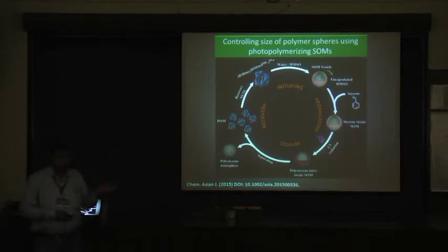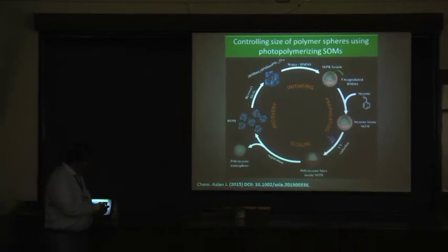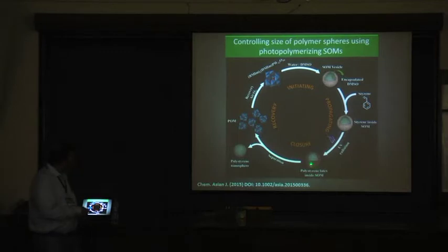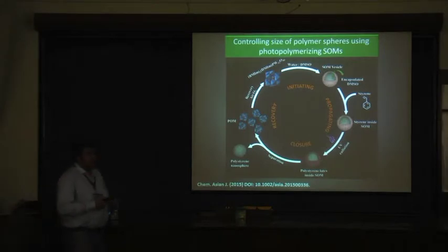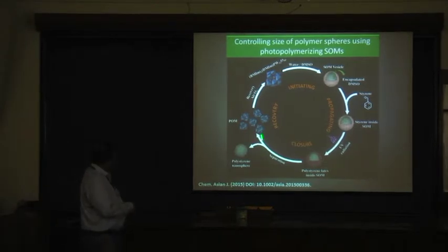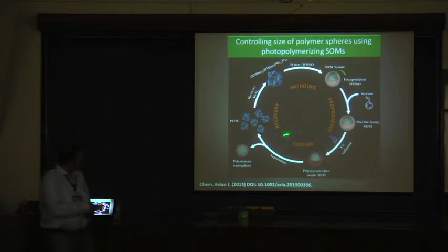And then they polymerize the inner content. Now, you have a hydrophobic core and a hydrophilic oxometalate shell. They do not like each other, so they phase separate. You have a macroscopic phase separation, and then you can recover this, but it is in the reduced state. So, you put it in air, and you get it back in the initial state.